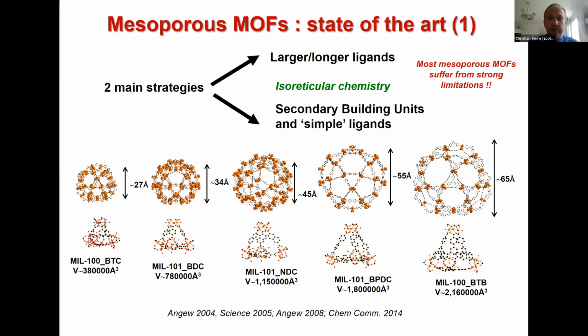For mesoporous MOFs, this is a brief reminder of the state of the art. There are two main strategies to construct these solids. Either you use extended ligands and a simple building unit, or otherwise you use a simple ligand and then make a secondary building unit, and then you assemble these to construct a mesoporous solid. And you play on the isoreticular chemistry to change the pore size. But as in this case with the iron MOF, for instance, if you take the smallest one, it is hydrothermally stable. But as soon as you increase the pore size and the ligand, then the chemical stability decreases drastically. So it means that most mesoporous MOFs still suffer from strong limitations.